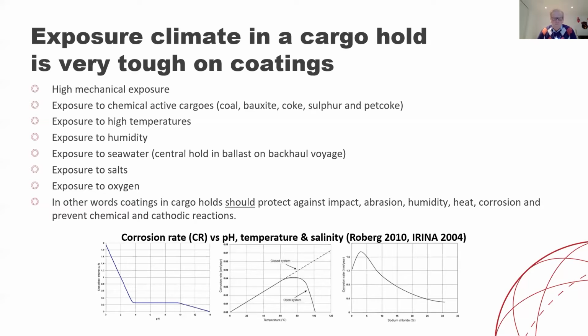And below you can see some curves where you have plotted corrosion rate as a function of pH, temperature, and salinity. At low pH, you can see that corrosion rate increases a lot in acidic conditions, as you can have if you, for instance, are carrying coal and you have humidity in your cargo, you get sulfuric acid created in the hold, and you will get these low pH conditions. Temperature has a big impact here, and it falls off around 80 degrees C. So if you are carrying a warm cargo, of course, you will have more corrosion due to that. And then salinity. You can see here that corrosion rate goes up to about 3.5% salinity, which is the typical salinity in seawater, which you would then have if you are using one of your cargo holds for ballast.